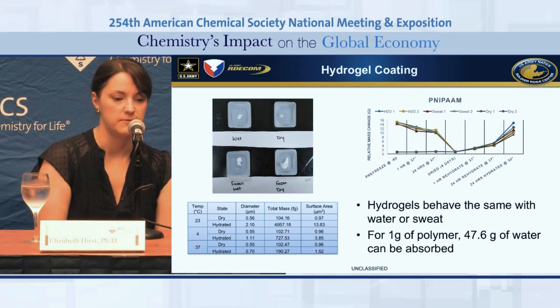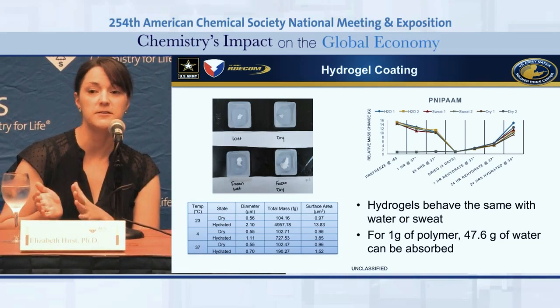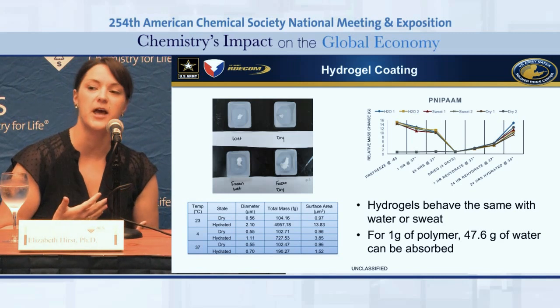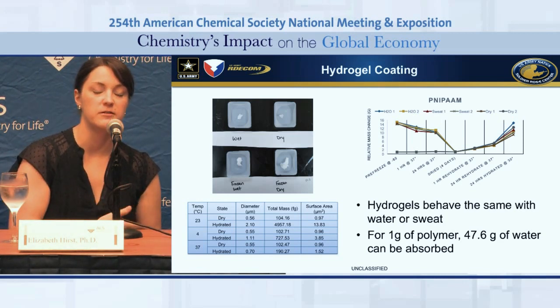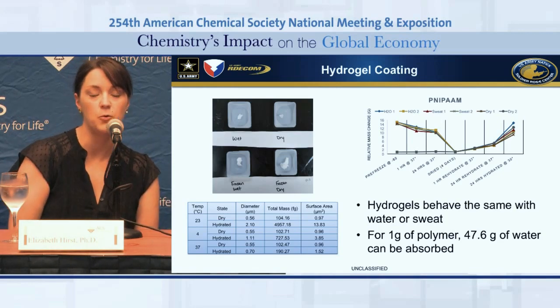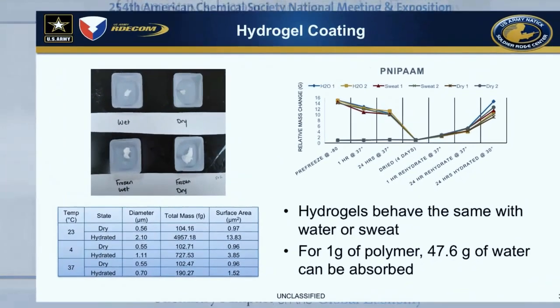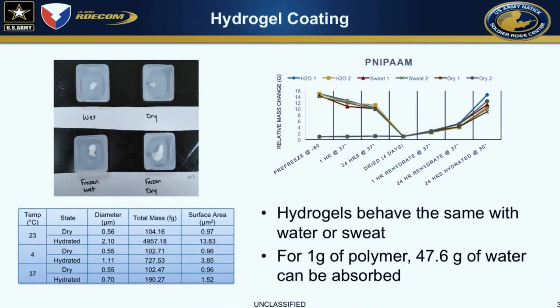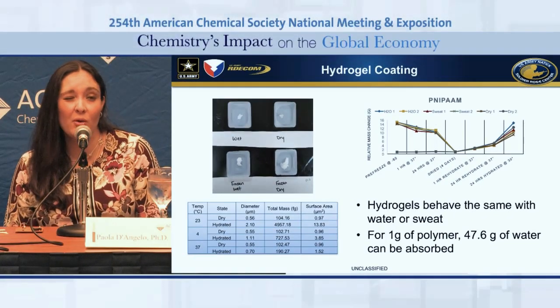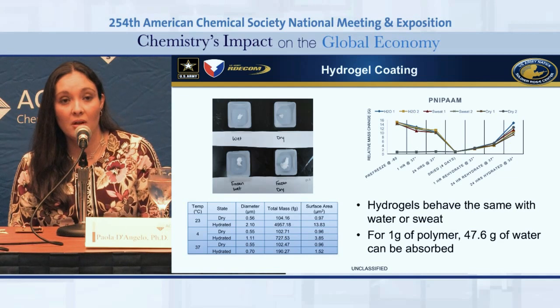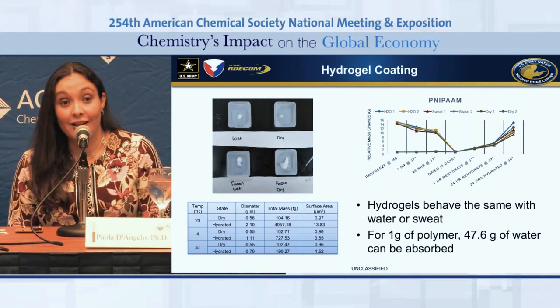And there are some examples of people using hydrogels for extreme heat to help maintain moisture. So there's actually firefighter jackets that have polyurethane hydrogel liners to help keep the firefighter cool. So we're just simply hoping to take that same technology and apply it to the different end of the temperature extreme. And I guess it's worth mentioning that the hydrogel that Liz has started developing can absorb as much as 40 times its weight. So 1 gram of hydrogel powder is able to absorb about 45 grams of water. So the potential is there.